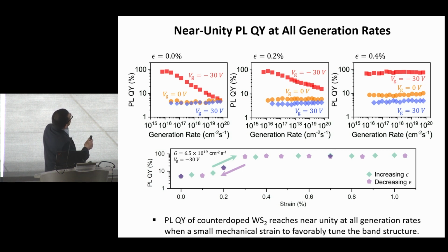Now, in the previous slides, I showed you that we can make the luminescence quantum yield very high at low generation rates, but the key is to get them to be high at high generation rates. When the generation rate is high, you have a lot of excitons. The exciton concentration in the material builds up. And when you have very high exciton concentration, now you can get exciton-exciton annihilation. One exciton can transfer its energy to another exciton. You form an excited exciton, and that thermalizes. So that's a non-radiative process.